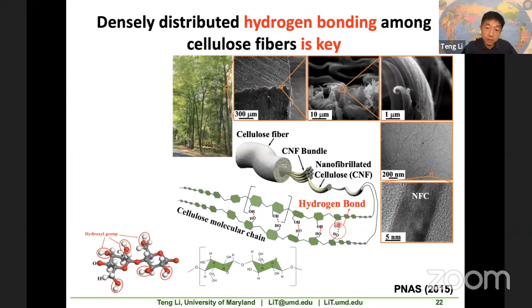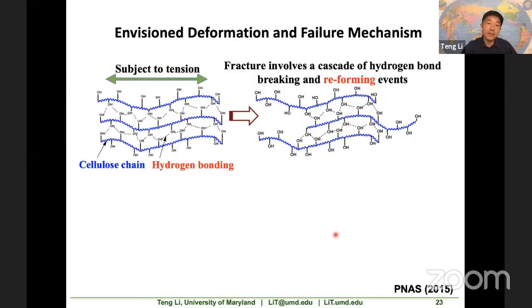So if you put these two OH groups close to each other, they naturally form and they can reform, which means that when this OH group is moving to another neighboring OH group, they naturally form a new hydrogen bond, okay? So with this in mind, we envision the deformation and failure mechanism of the cellulose nanopaper. Now, when you try to stretch the cellulose nanopaper in a tensile test, the individual cellulose chain won't be breaking because we know that the intrinsic strength of cellulose chain is very high, several gigapascal.